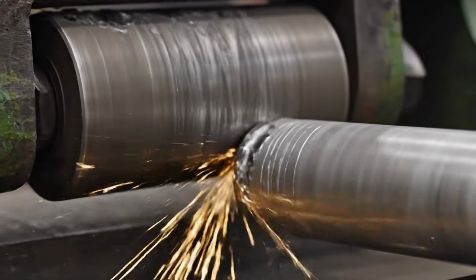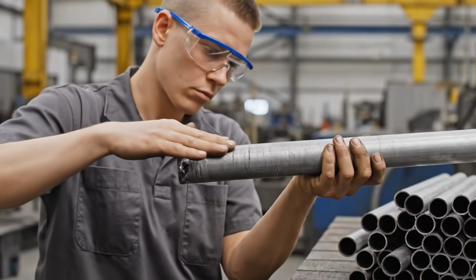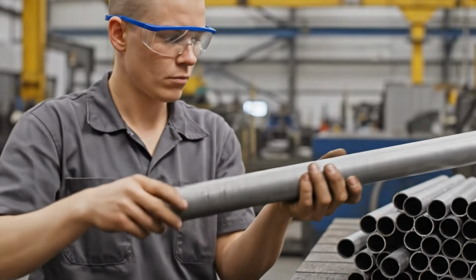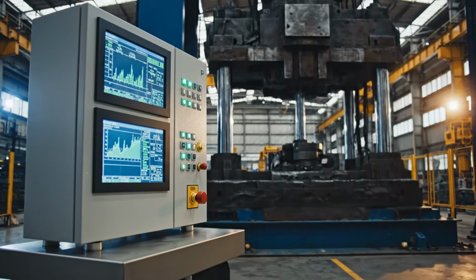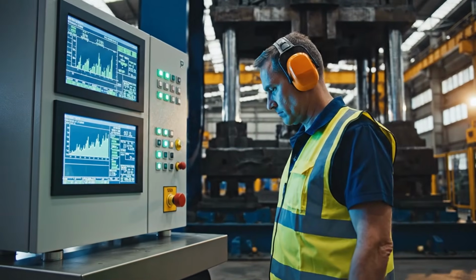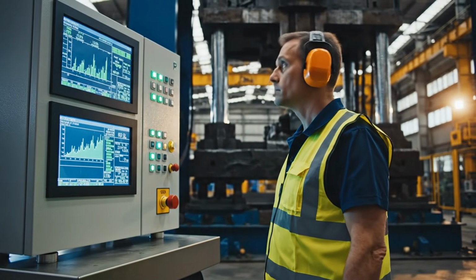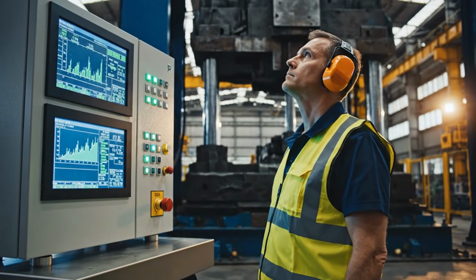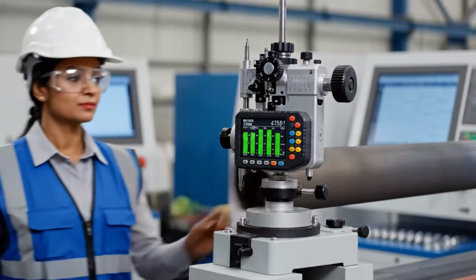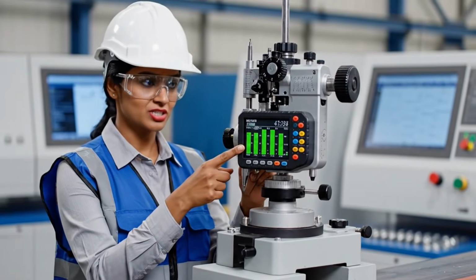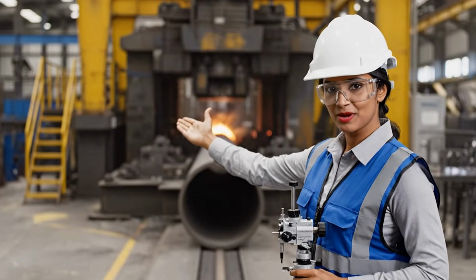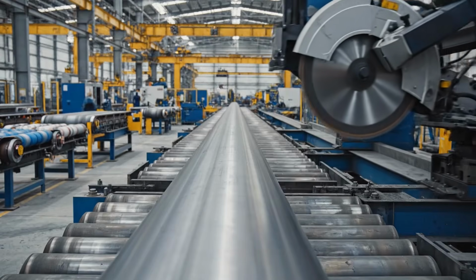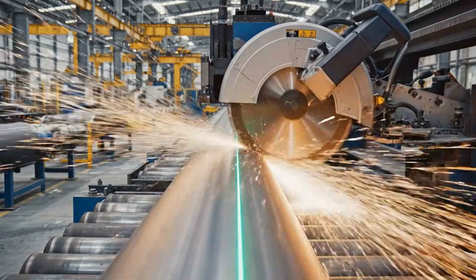After the main rolling, the tube passes to a sizing or stretch reduction stage. Here, the outer diameter is adjusted with more precision. A sequence of cages with small contact rollers gradually reduces the tube. The relative speeds between stands are coordinated to impose a certain longitudinal traction. That traction helps to stabilize the piece, refine its measurement, and obtain an even greater final length.